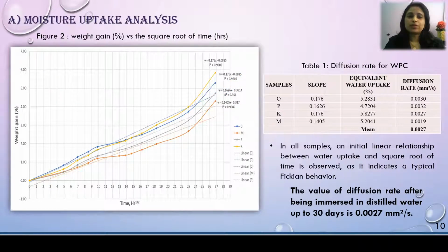The evaluation of the water absorption profiles as a function of square root of immersion time in hours is shown in this graph. In all samples, an initial linear relationship between water uptake and square root of time is observed, which indicates a typical Fickian behavior. From this graph, the rate of diffusion is calculated using equation 2. Hence, it is found that the value of diffusion rate after being immersed in distilled water for up to 30 days is 0.0027 mm square per second.